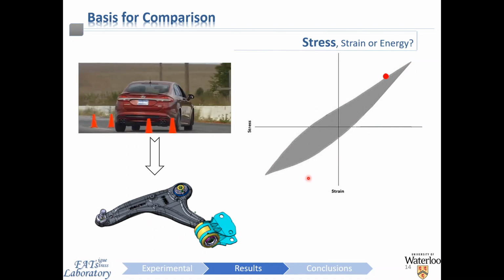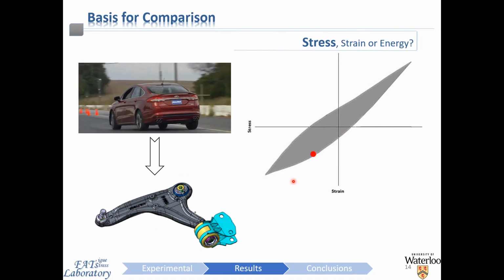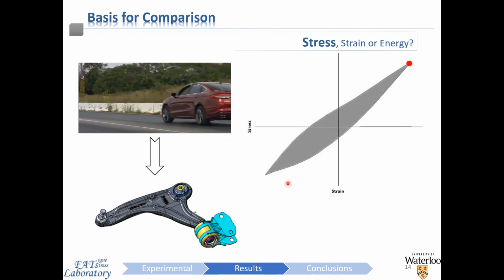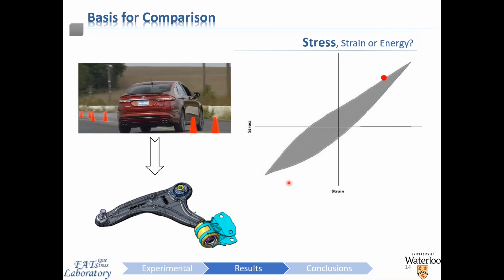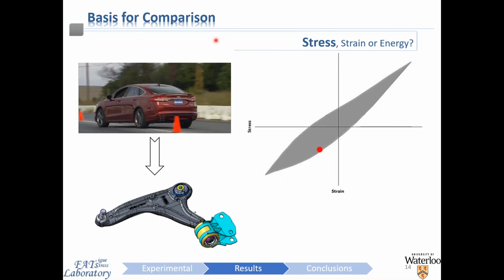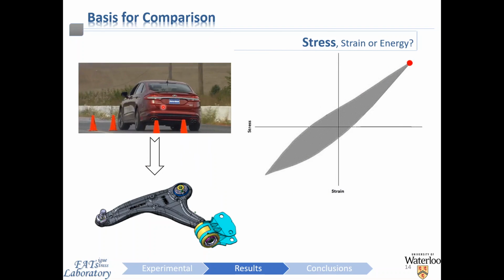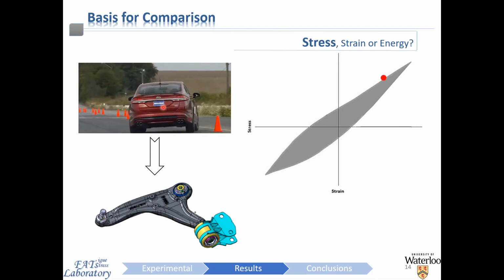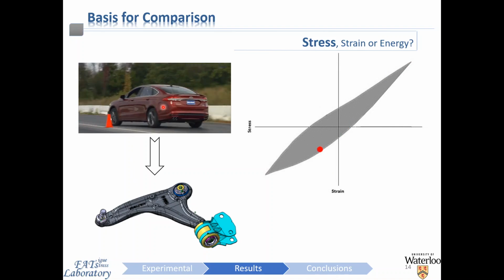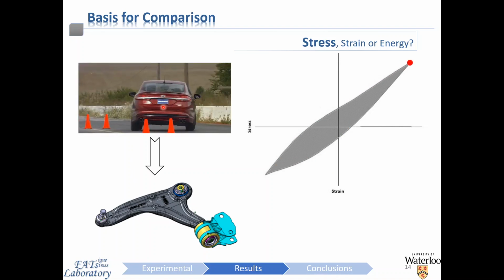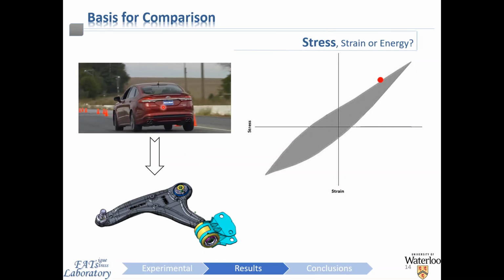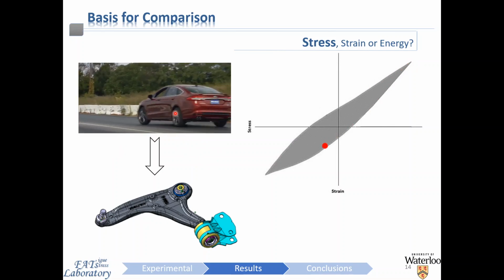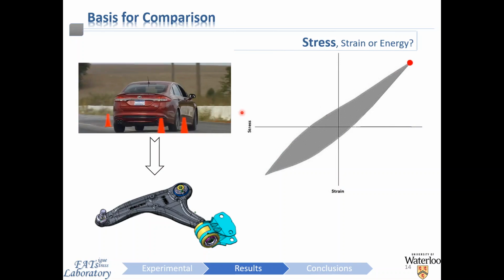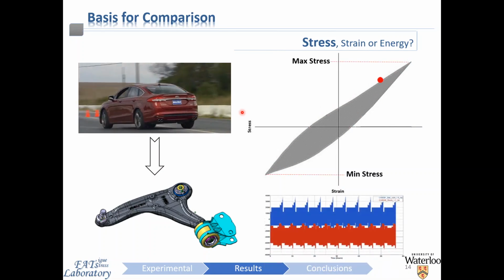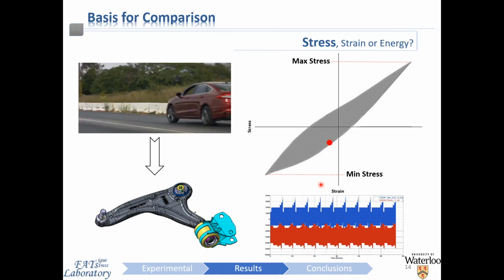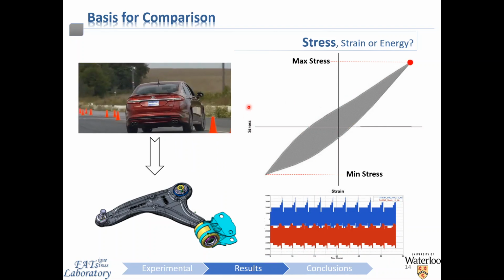So for the first basis of comparison, it begins with the actual loading history for the application. So the loads will be realized as stresses and strains within the component at the material level. The application is an automotive suspension control arm, as we can see here. So in order to simulate this type of real world behavior, we implement a variety of different laboratory style tests, which use fully reversed loading over a wide range of amplitudes to characterize the material behavior. As the vehicle undergoes individual cycles within the fatigue block, as we can see here, the material is undergoing cyclic hysteresis as indicated by the loop on the right here.